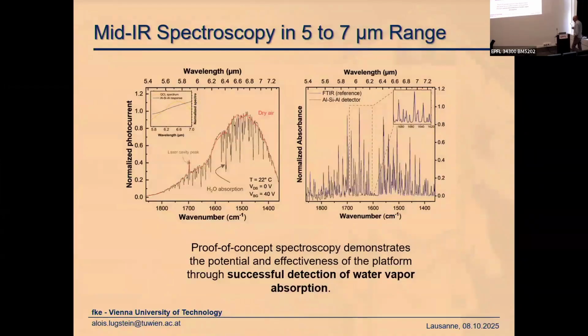And finally, he inserted this detector in an FTIR system to detect the characteristic lines of water vapor. This is a comparison of the Al-Si-Al photodetector with a reference detector of the FTIR. And you see that we have a perfect fit with this reference detector of the FTIR.